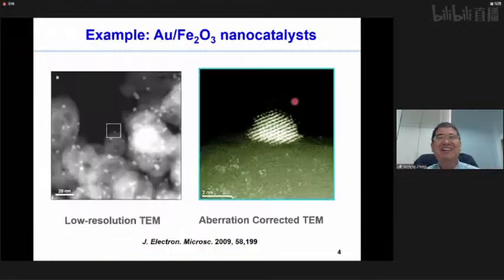Okay, here is a typical TEM image of gold nanoparticles supported on iron oxide. At the left-hand side is the low resolution TEM. You can see the white dot here represents one nanoparticle. But with the development of advanced aberration-corrected TEM, besides these big particles, we can also see some single atoms or even several atoms coming together to form small clusters. All these species would not be observable using low resolution or conventional TEM.